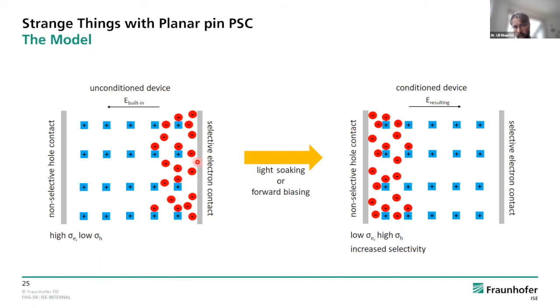So what I can say is the implementation of mobile ionic species led to the fact that the presence of these mobile ionic species changes the built-in voltage, the electrical potential distribution, and this has an impact on the distribution of electrons and holes. And as we have learned before, the distribution of electrons and holes, and especially their conductivity, is ruling finally if you have a lot or not so much surface recombination. So first of all, we call this unconditioned, and then after light soaking, when the open circuit voltage is high, we call it conditioned device.